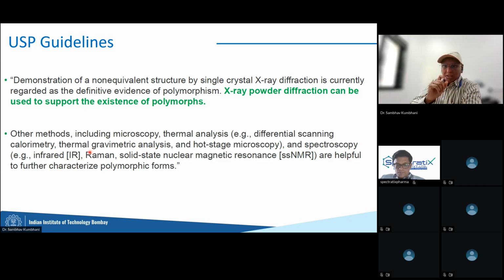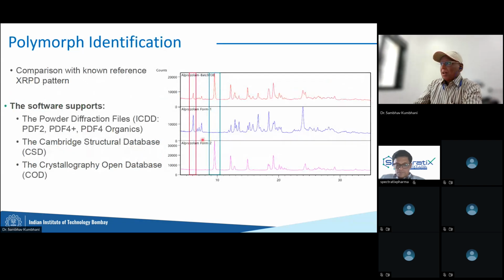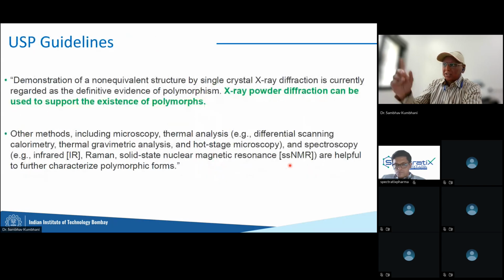But the limitation is it has to be a pure single crystal, whereas the advantage of powder XRD is it can have a mixture of things. So a single crystal XRD cannot measure this batch. It can either measure form 1 or form 2 only. This is where powder XRD is used. I hope this makes sense.